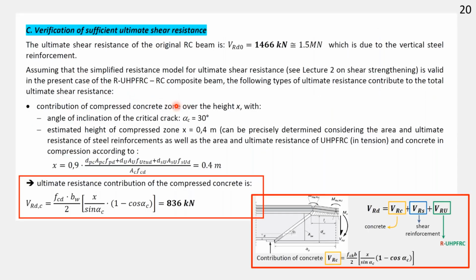Similar for shear. And for shear, we have developed already some years ago a resistance model, which is the summation of the contribution of concrete, the steel reinforcement, the vertical one, consisting in our case here of stirrups and, of course, the post-tensioning steel. And then there is also a third contribution due to the existence of the UHPFRC layer here, this membrane that has actually the function to confine our reinforced or post-tensioned element here in order to activate higher shear force, higher shear resistance, in particular the contribution of concrete.